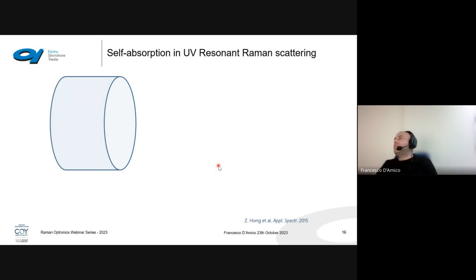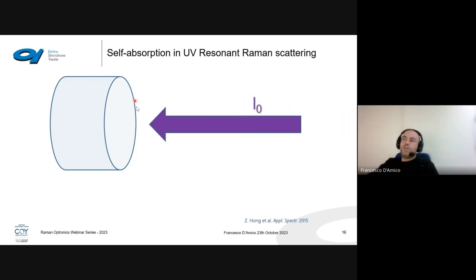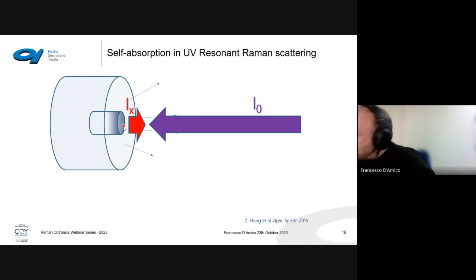Just a slide about the monochromator, but you know. Let's talk instead about self-absorption of the sample, which is strongly related to possible photo damage of samples in the ultraviolet. Basically, if we send an incident radiation to a sample, the emitted light comes from a specific scattering volume. This volume is a certain amount because light enters into the sample, but the attenuation increases as the beam enters, and also the diffused light that exits from the sample is affected by this attenuation.